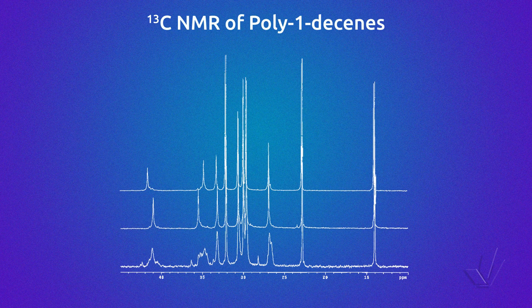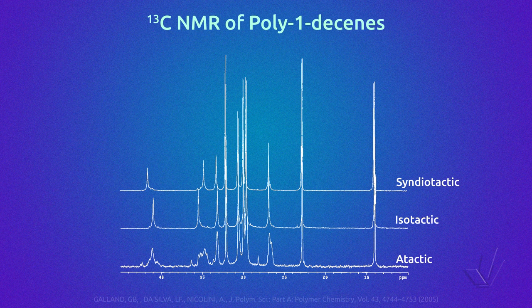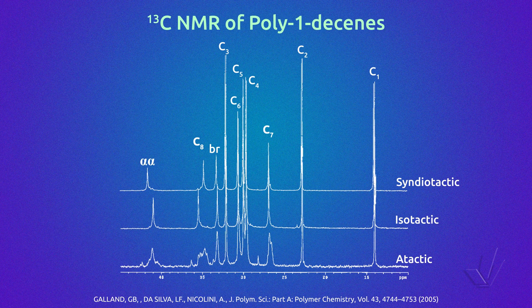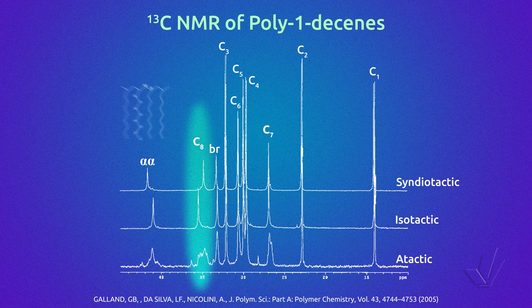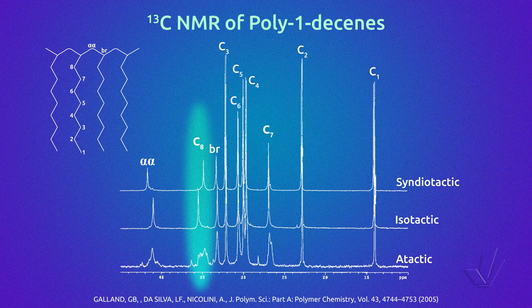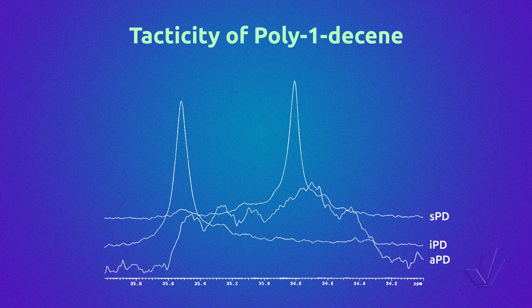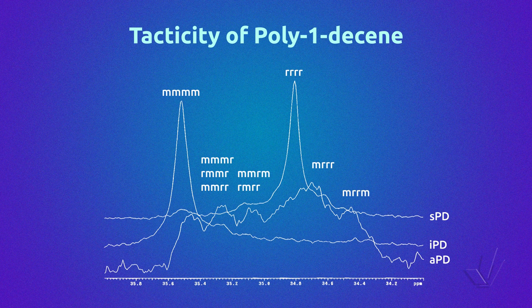All polymers with a pseudo-chiral atom can present tacticity. In general, all vinyl polymers with one substituent have stereoisomers. As in the case of polypropylene, the carbon used to study tacticity is the alpha carbon adjacent to the tertiary carbon. Here we can see carbon-13 NMR spectra of poly(1-decene) with different tacticities — atactic, isotactic, and syndiotactic. The carbons most influenced by configuration are C7, C8, and the alpha-alpha carbon, but the lines are most clearly split in carbon-8, which is the carbon alpha from the branching carbon.